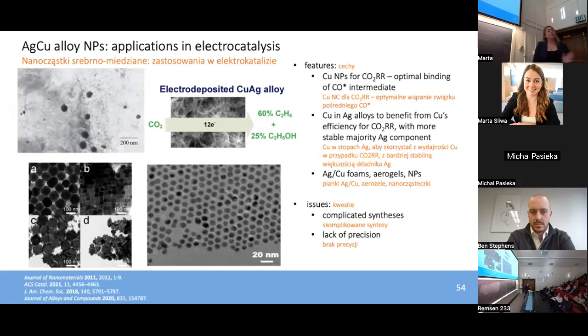So one workaround, lucky for us, is alloying copper with silver, which is a much more stable material. In this configuration, we can marry the catalytic activity of the copper with the stability of the silver. This has led many to synthesize silver and copper containing materials for electrocatalytic reactions, such as silver copper foams, aerogels, nanoparticles, and other structures. However, the techniques used to make these systems are typically very complicated. They require high temperature reduction, multi-step seeded growth, or electrodeposition of precursors that are then embedded in these matrices where we can't isolate those products out from.